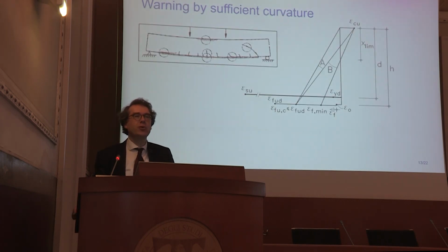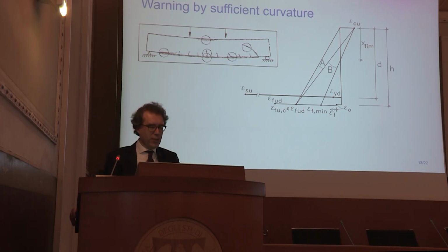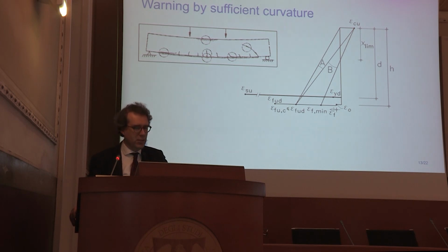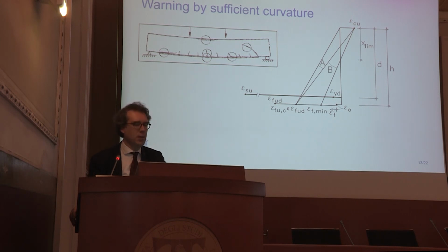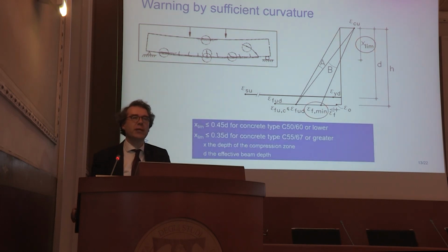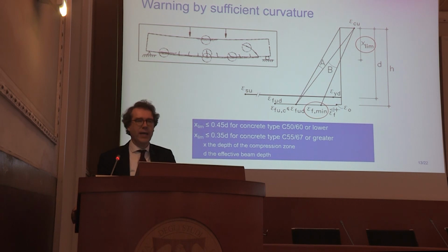When designing and using these strengthening systems, technologies, we need to account for different failure aspects which can happen. So it becomes at the end not always clear, especially because FRP materials being a linear elastic material, if we have sufficient deformability at the end. So typically we introduce in our design philosophy a check on the curvature or the depth of the compression zone, if you want, so that we have sufficient curvature, sufficient warning effect according to these equations you can read here on the screen.